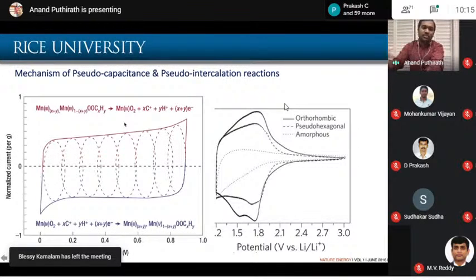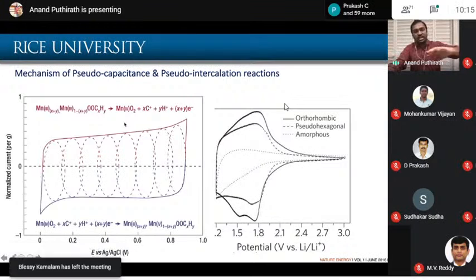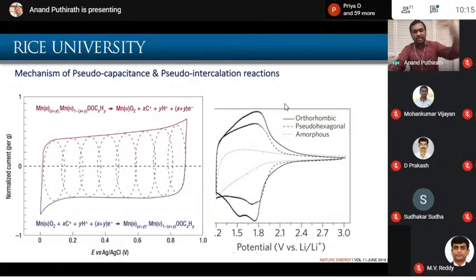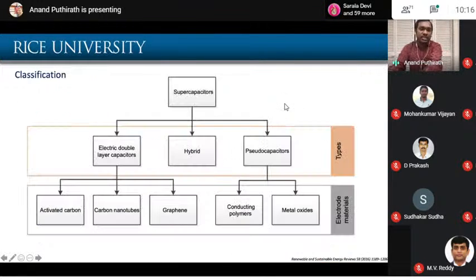And this is a stochastic process, right? Charges will get adsorbed and they will come back and then go again, because it's a partial oxidation reaction. You might see a flat curve even for a pseudo-capacitive material, but what is happening inside is multiple oxidation reductions. And if this frequency is very fast, they may not be resolved, and our instrument cannot read that specific oxidation reduction, but it will give an average current.